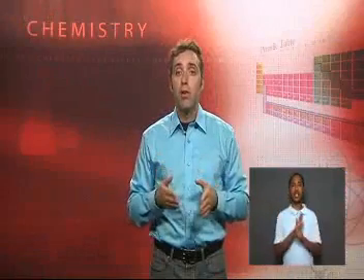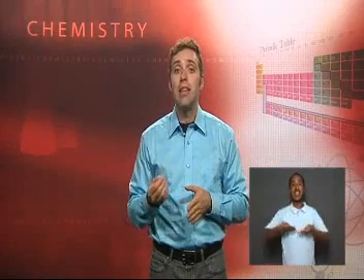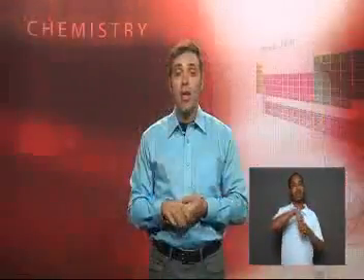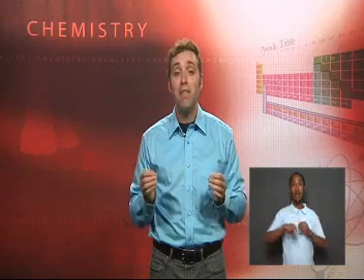The oxides of silicon, phosphorus, and impurity metals combine with lime to form slag. The charge in the converter remains in the molten state by the energy that is released in these oxidation reactions. The converter is tilted to remove the slag, and after a second blow of oxygen, it is tilted once again, and the molten steel is poured out. The basic oxygen process only takes about 25 minutes.